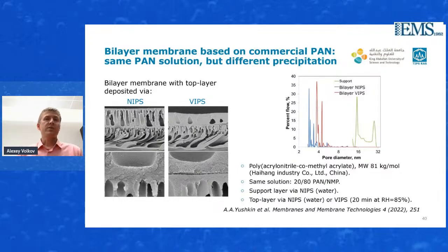In other words, we can optimize to make a highly permeable support material by using the first stage. And on the next stage, we can just make a tunable porous selective layer with the desired pores and molecular weight cutoff. In that case, we don't need to think about how to make a nice selective layer together with the support layer as well.